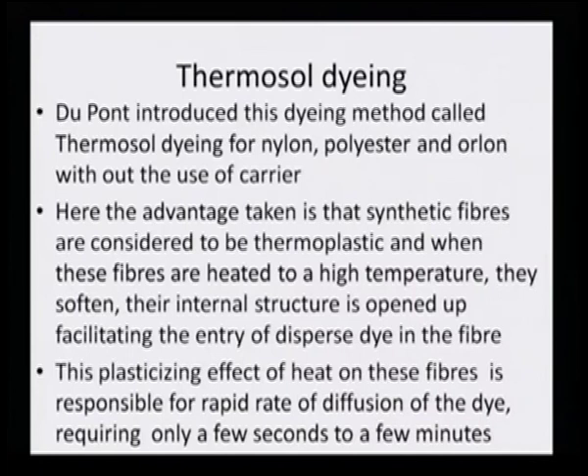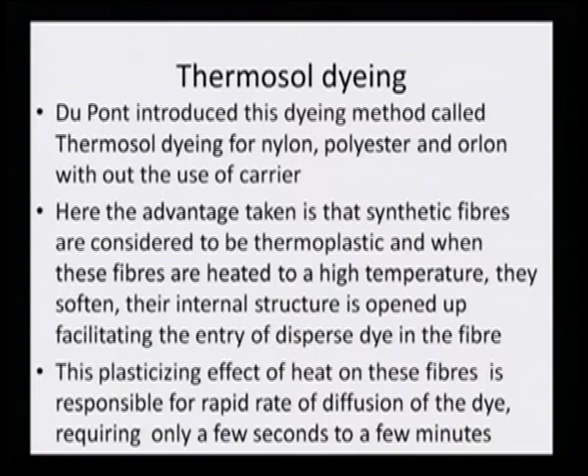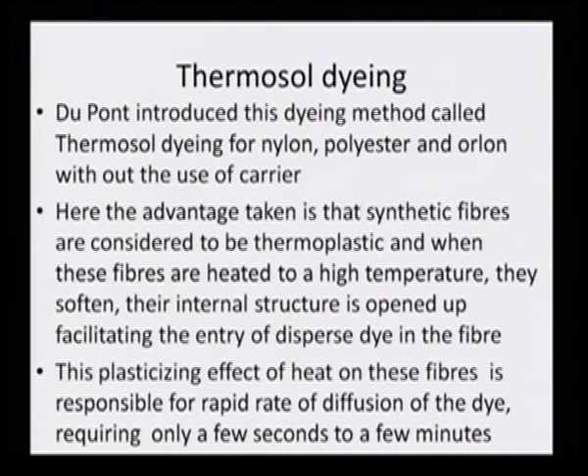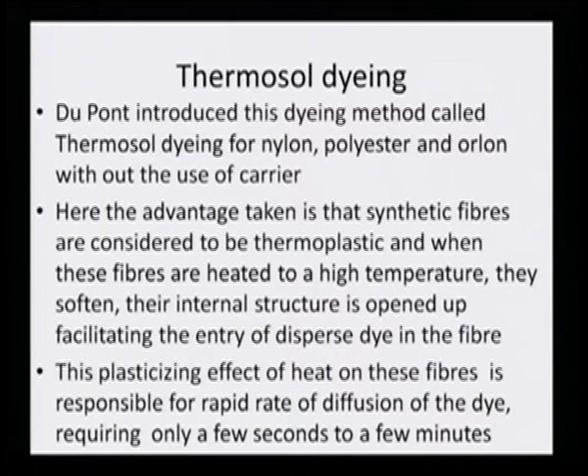Therefore, a new process called thermosol dyeing was developed. Du Pont introduced this dyeing method for nylon, polyester, and orlon without the use of a carrier. The advantage taken is that synthetic fibers are thermoplastic. When these fibers are heated to a high temperature, they soften, their internal structure opens up, facilitating entry of dispersed dye into the fiber. This plasticizing effect of heat is responsible for rapid diffusion of dye, requiring only a few seconds to a few minutes.